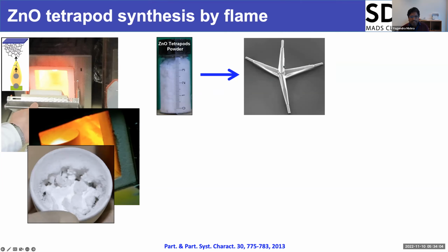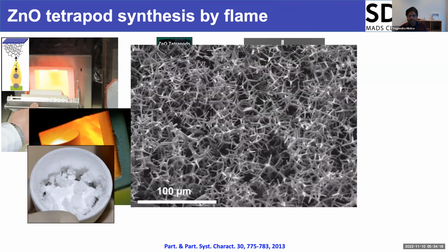The diameter of each arm is around 1 to 2 microns, and the length goes up to around 2 to 10 micrometers. So they are micro. I will tell why they are nano as well, but we have the possibility to make them into the nanoscale in different forms. So here you see a typical image of a three-dimensional assembly, the self-assembly nature of these tetrapods. They assemble themselves like popcorn in the bucket when you go to watch a movie. In the same way popcorns self-assemble, these tetrapods assemble with high porosity.